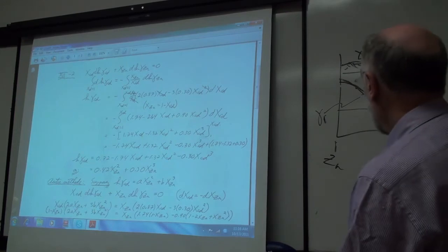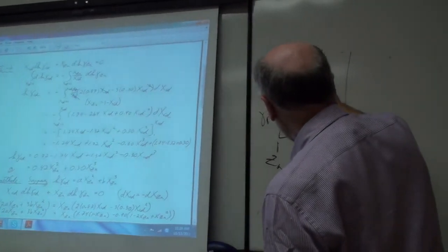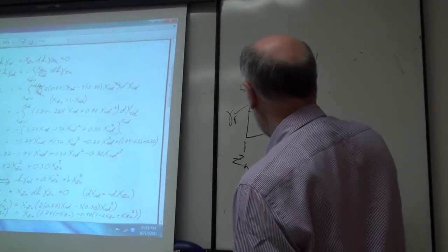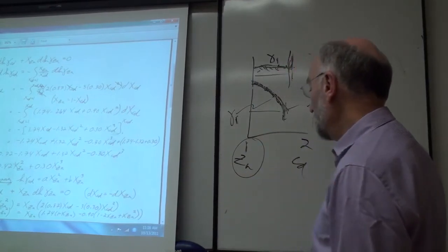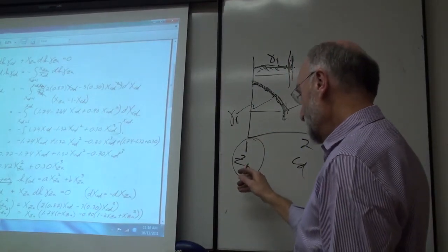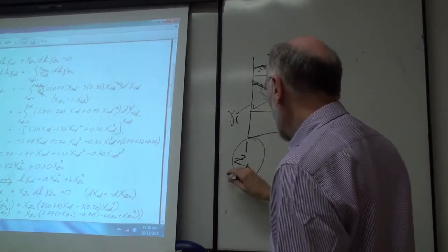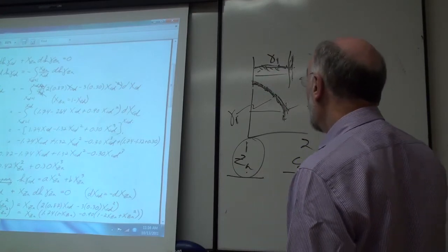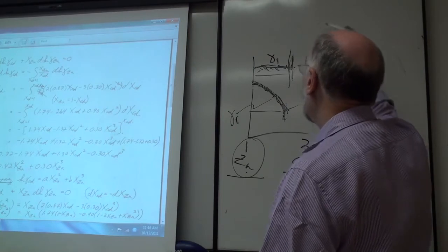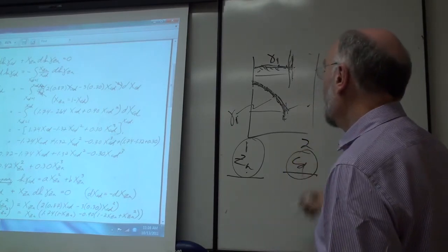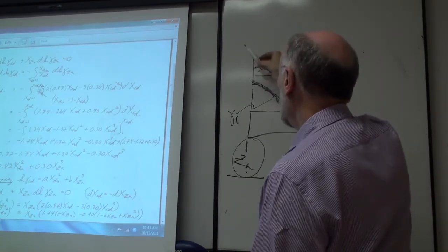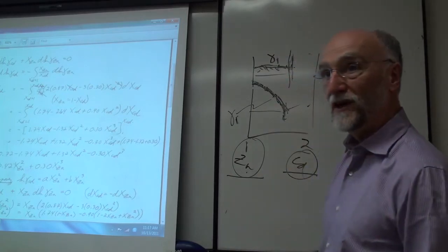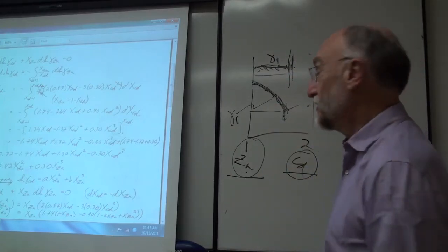So remember that if you have a phase diagram and you're just using the liquidus up here, that liquidus gives you the activity coefficient of the solvent. Okay. If you then fit that up to an equation and you get the activity coefficient of the solute, and you don't have any other data to fix the endpoint, then the slope might be right, but you don't really know the actual value. And you see this all the time.